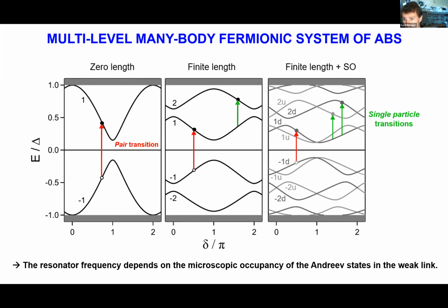And so in this case, one really has to deal with the full multi-level nature of the Andreev spectrum and the spin character of the levels. What's important here is that the resonator frequency is shifted because of the coupling with the Andreev levels, and this shift depends precisely on the microscopic occupancy of the Andreev states. So by sending microwaves, we drive transitions between these states, and so we change the resonator frequency shift. And this is what's used in microwave spectroscopy.